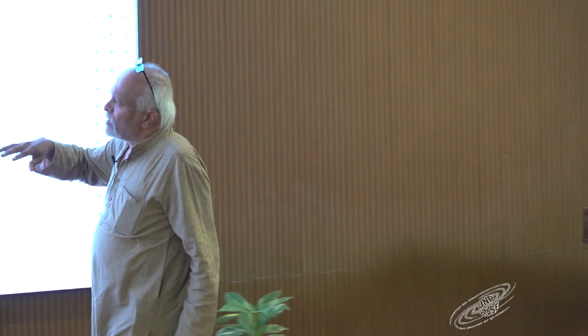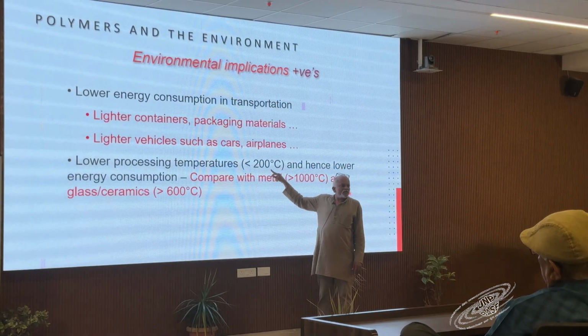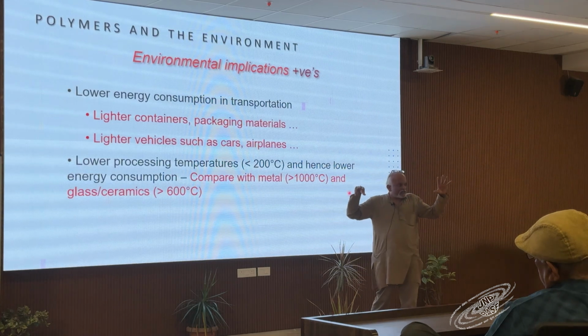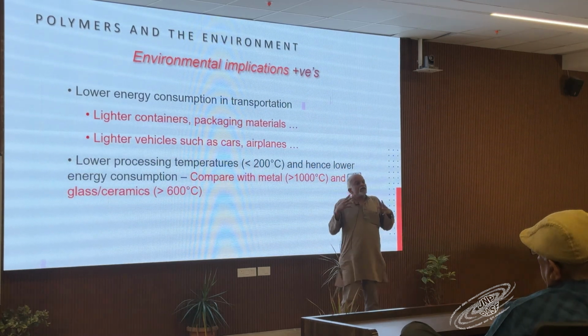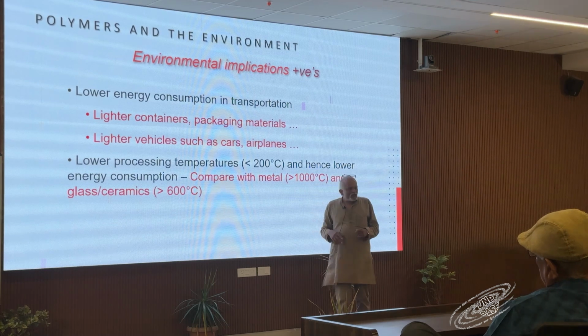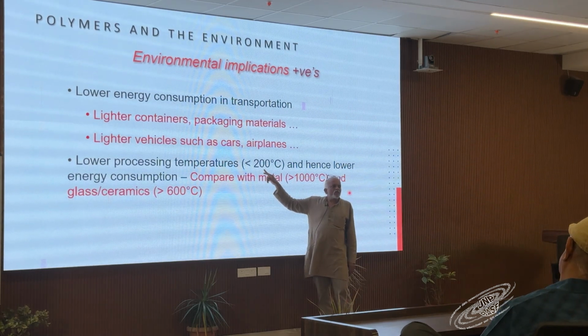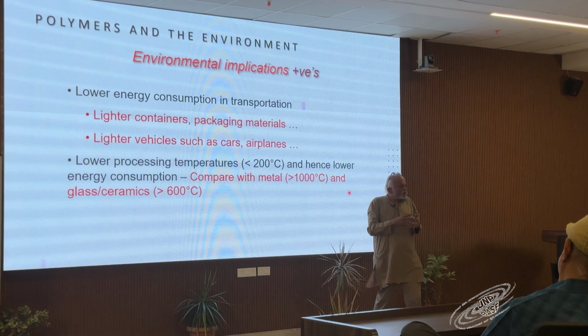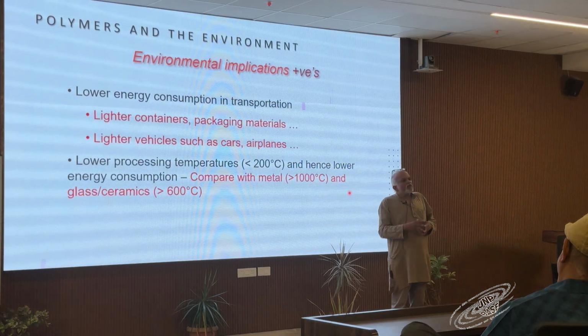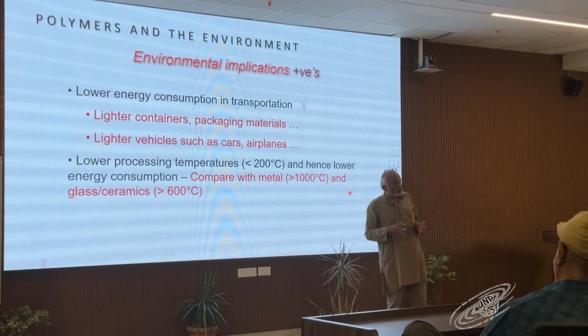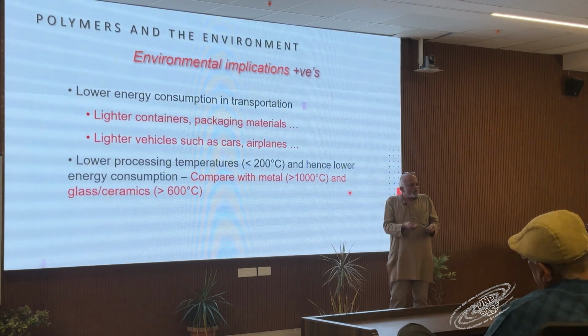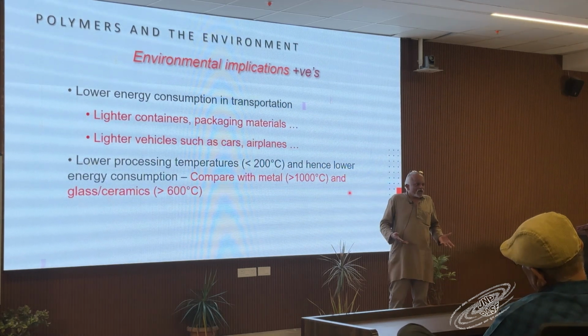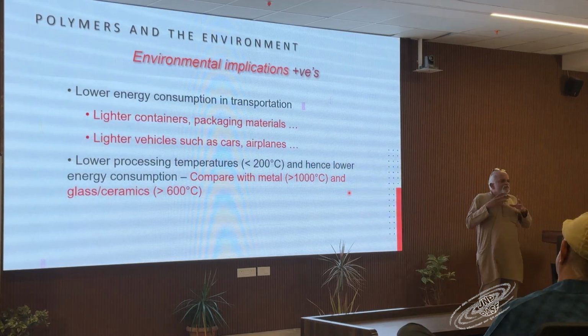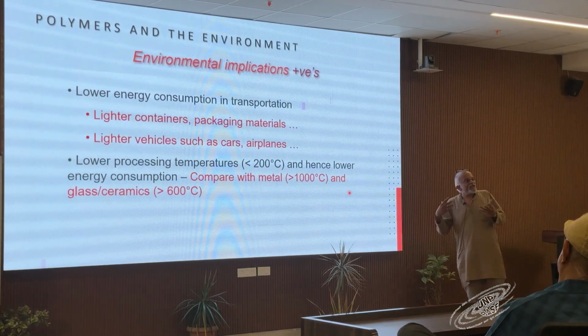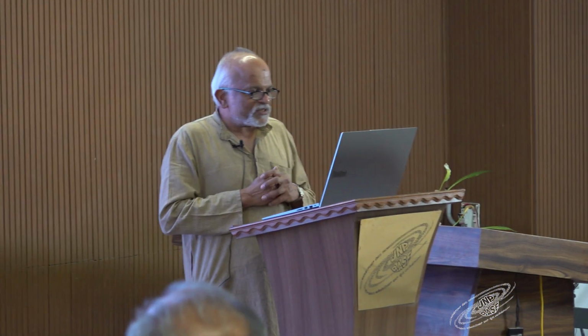And the beauty is that the processing temperatures, unlike iron, which has to be taken to 1200 degrees centigrade, heating anything to that temperature requires a lot of energy, correct? So here polymers are processed typically at temperatures below 200, which means the amount of energy required to process it is far smaller than the amount of energy to process metals or ceramics. The more energy you use, the more environmentally unfriendly you are, because as of today, much of energy is being generated by processes that lead to carbon dioxide emission, and therefore it's an environmental hazard. So that's one big thing.